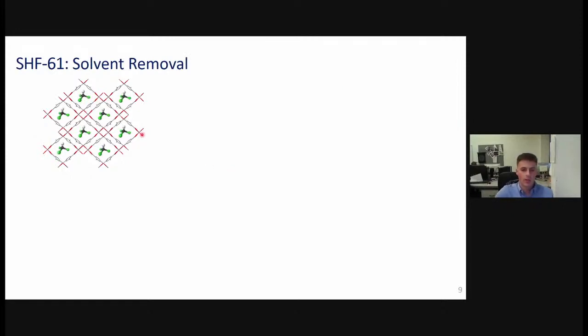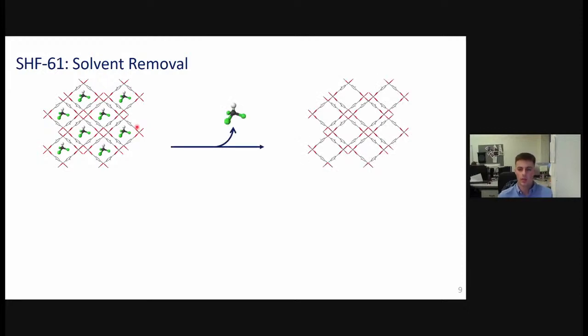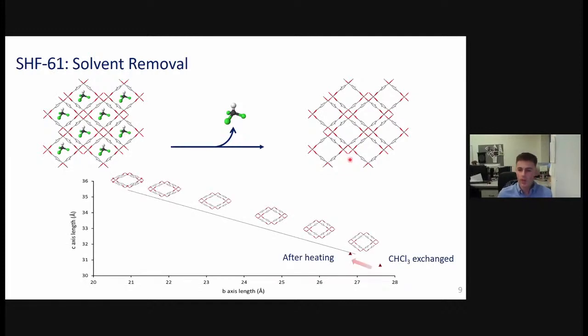So when we start with chloroform in the pores of the framework and we do the same thing again, so we heat up our single crystals of these, what we see is that actually there's very little response or very little change in pore shape. And again, we can plot those unit cell parameters overlaid with the graph we had previously, and we see that we only have this really small change in the B and C axis, so about an angstrom in both.